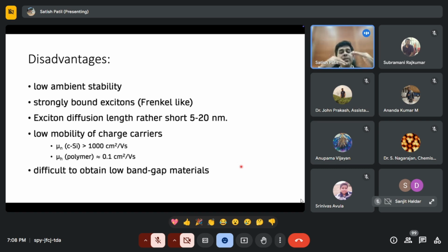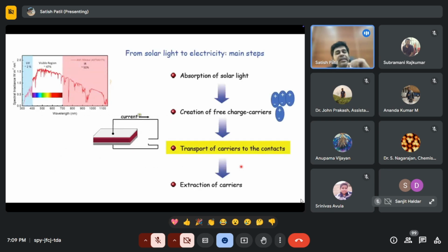The majority of organic semiconductors people use as of today have a band gap slightly higher than 1 electron volt. It's very difficult to make an organic semiconductor which is stable at ambient conditions and has a band gap less than 1 electron volt, because of these many side reactions. As an organic chemist in the audience, you understand that if you make the ionization potential and electron affinity smaller and smaller with respect to vacuum, you have a lot of side reactions. Unlike an inorganic semiconductor, silicon has a low band gap, 1.1 eV, but it is a very stable semiconductor.